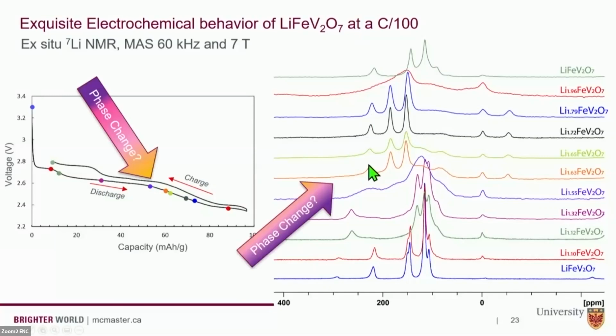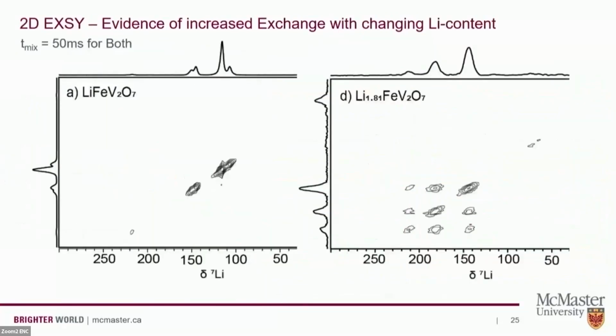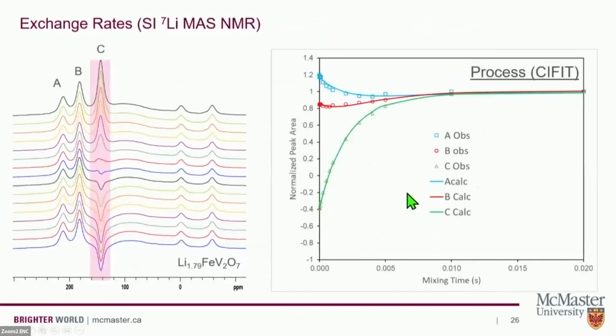What we did with this is examine this phase change first from the NMR point of view, looking at the local dynamics. So this is just simple EXSY experiments at 50 milliseconds mixing time for the original phase, and then the phase above that transition, so the electrochemically lithiated phase. We have nice evidence of chemical exchange around that set of 3 new peaks. And then we don't rely on EXSY to do this quantitatively because those experiments are really long. My group used a lot of selective inversion where we're simply flipping the C peak here and observing the change in intensity at A and B.